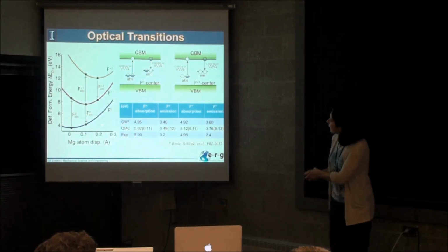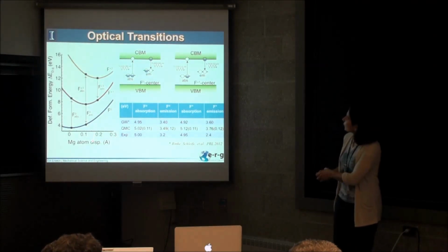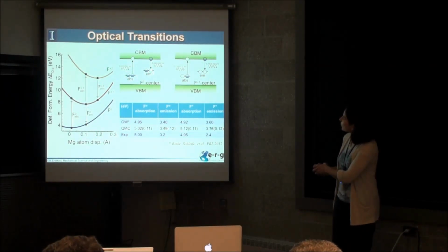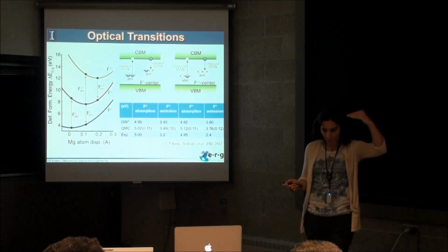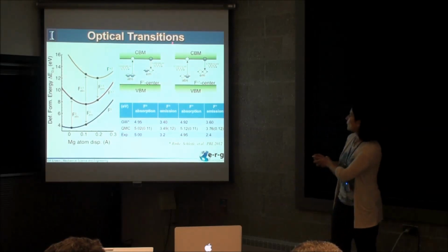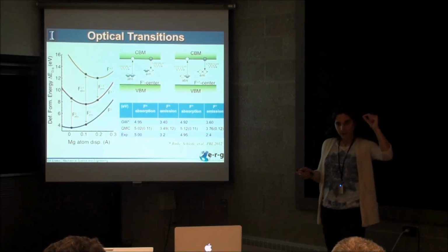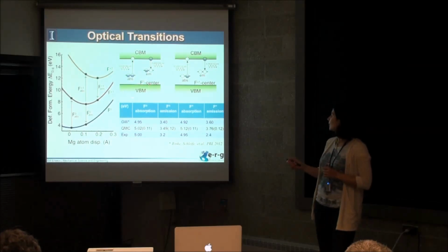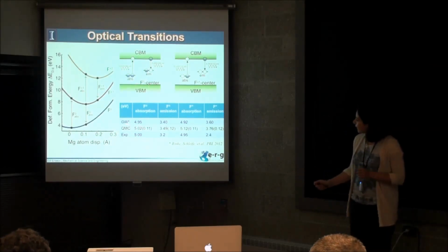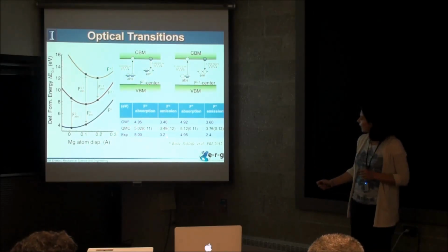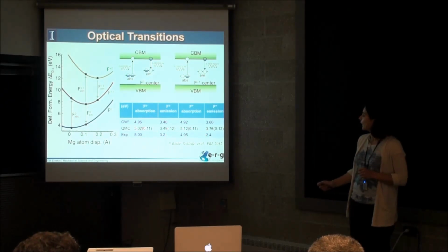This is actually really exciting to us, of these optical transition energies. And this says, when I have a defect present, is that defect going to absorb light of particular wavelengths or emit light associated with transitions in the charge states for that defect? And what's great here is those QMC numbers compare really nicely to the experimental numbers for the most part. They actually compare really nicely to recently published high accuracy GW results.